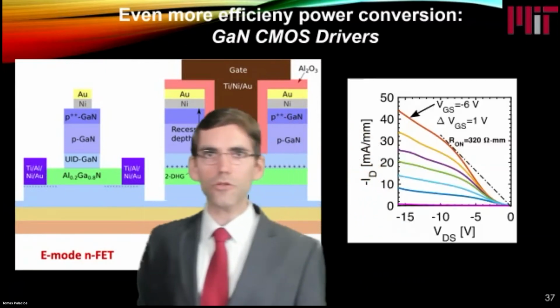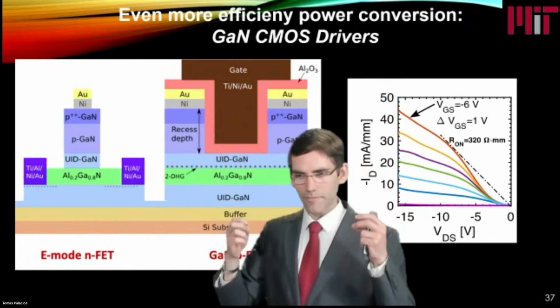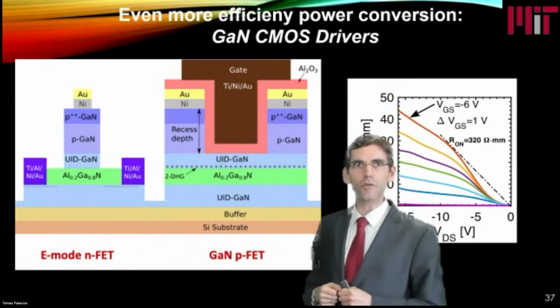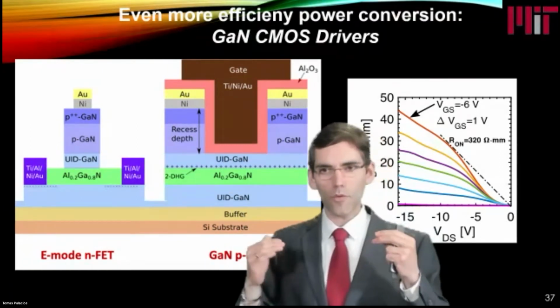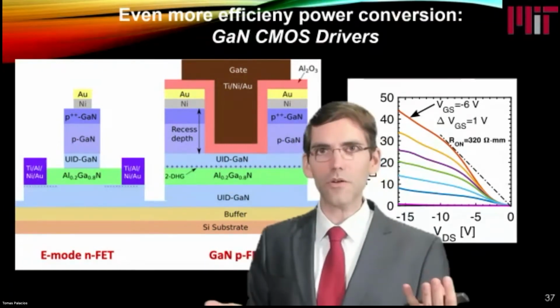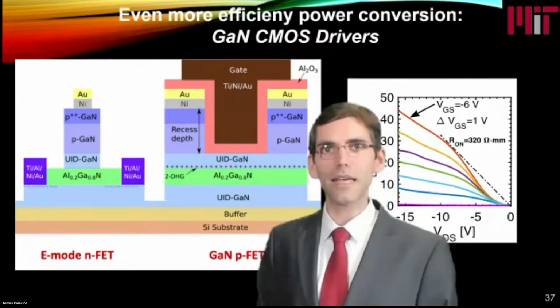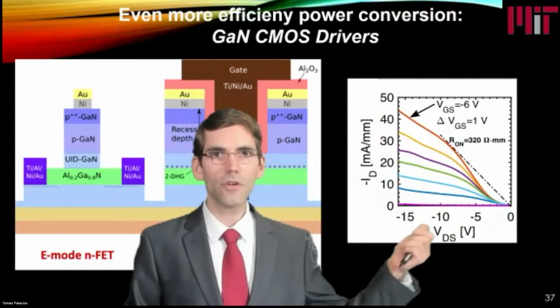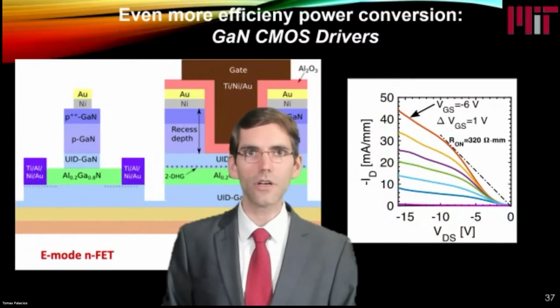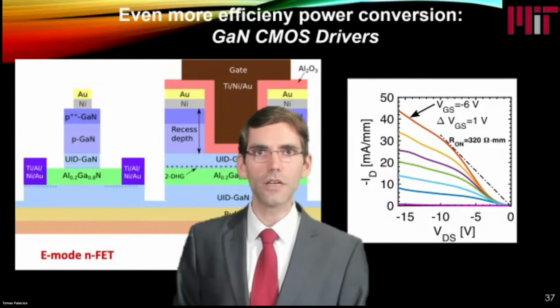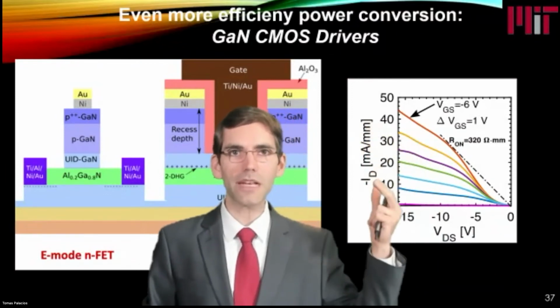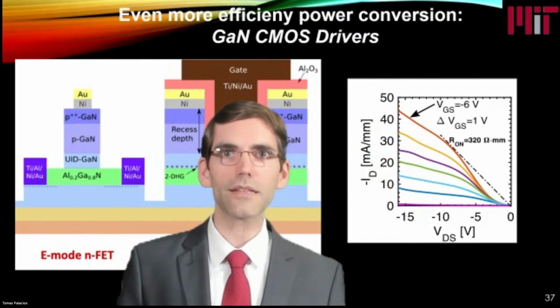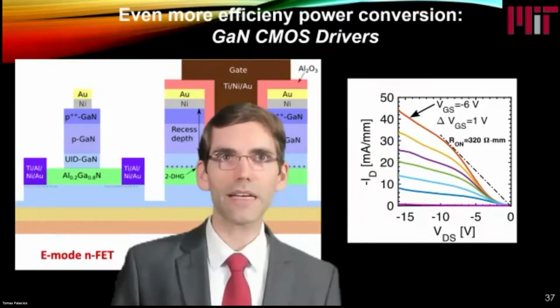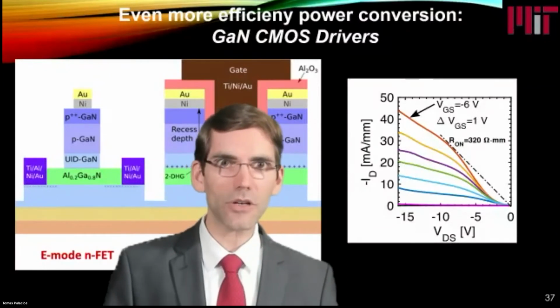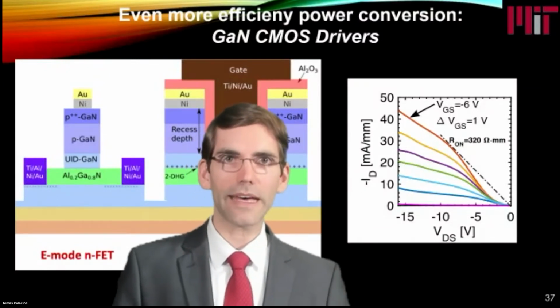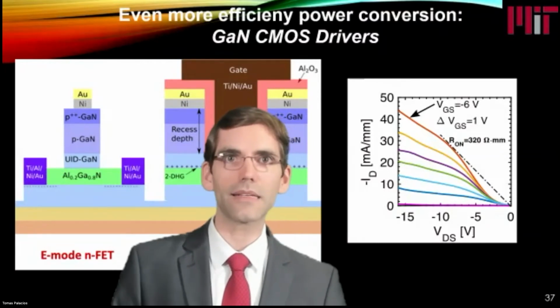In that way, we were able to demonstrate the first integrated CMOS circuit in gallium nitride, where we didn't need to use any kind of regrowth technology. We could just use standard epitaxial layers. And this is an example of a p-type gallium nitride transistor that we were able to fabricate with this structure. In this case, we had 40 milliamps per millimeter. Today, we have more than 400 milliamps per millimeter for these p-type devices, which are actually better performing than silicon p-type transistors at the same gate length.